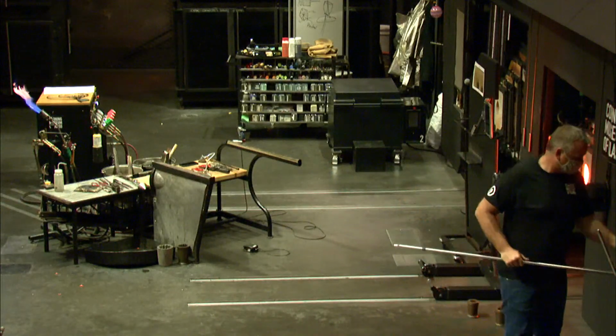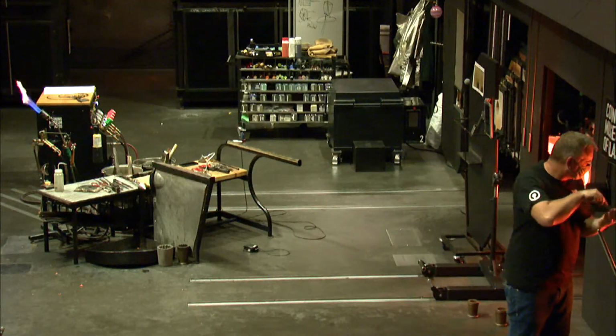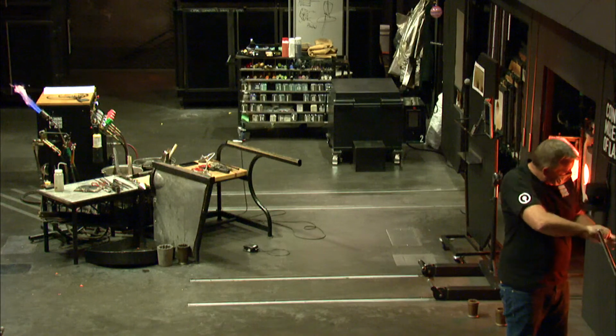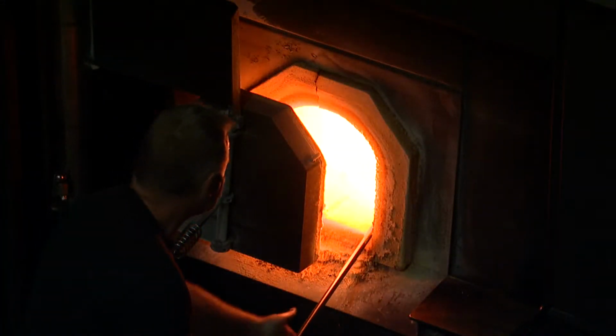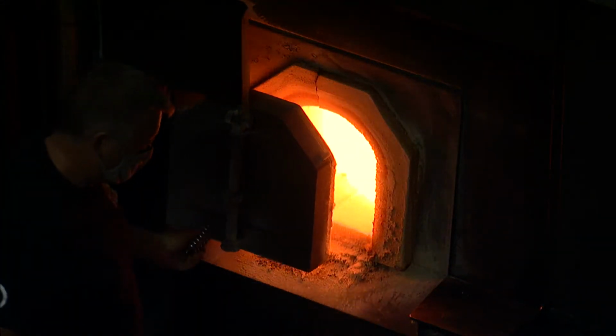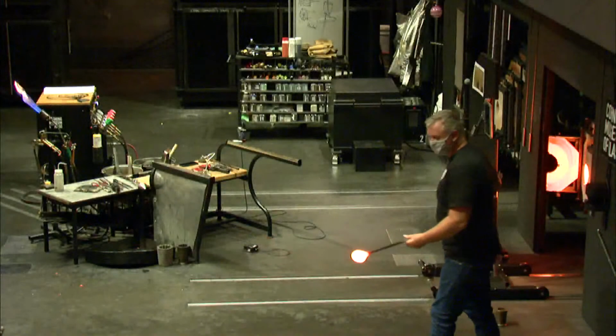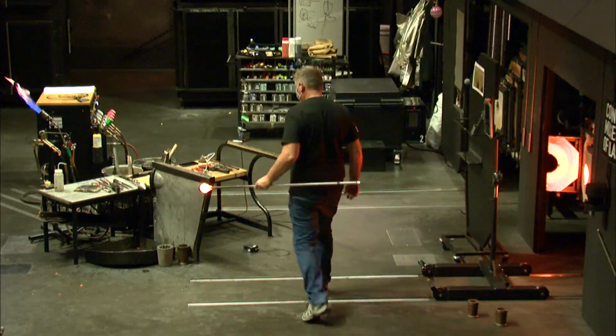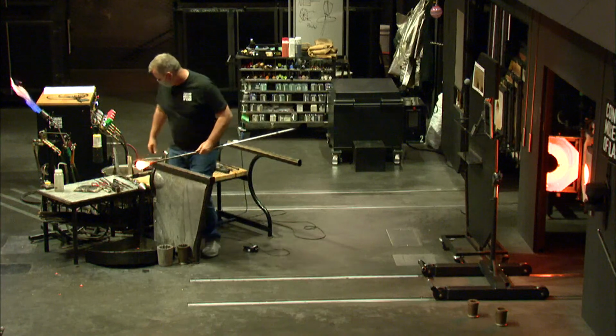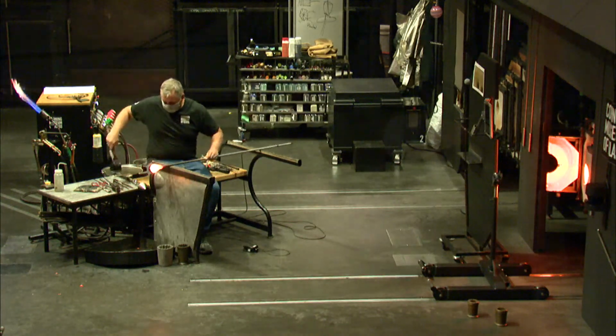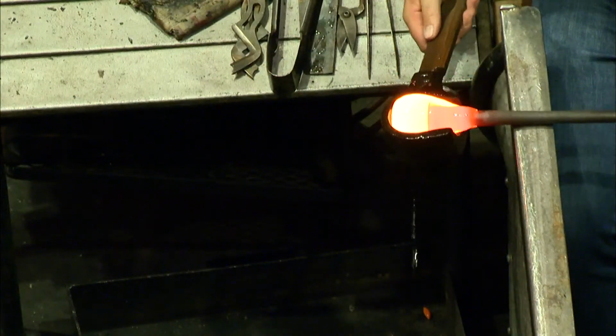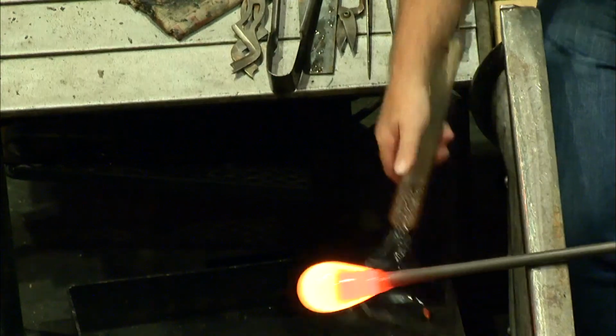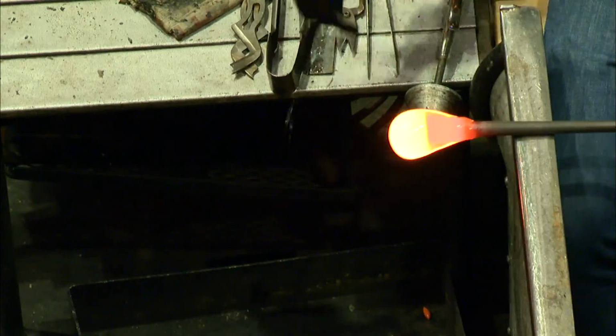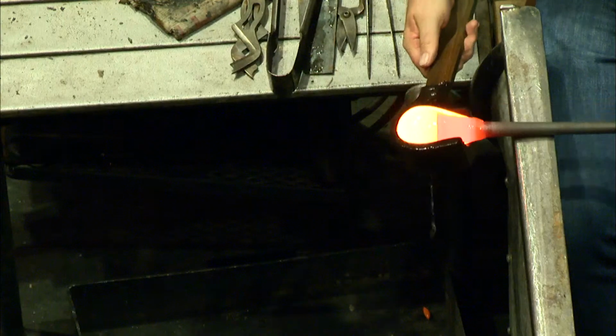If you have any form of undercuts or a flat surface on the top of your glass, you go in to collect more out of the furnace, you're going to tend to trap little bubbles of air just from the shape that it was in before you go in. Sometimes this can be a design element if you want to create a design of bubbles, like in this bowl right here, then you'll intentionally go in and create little dimples.